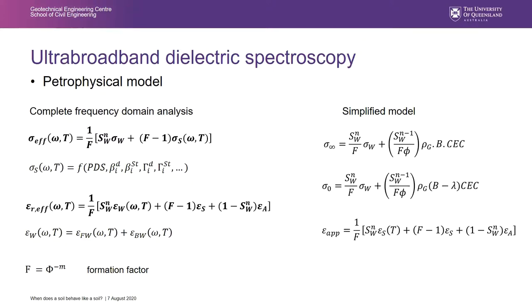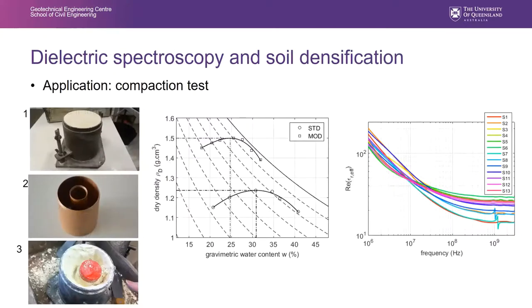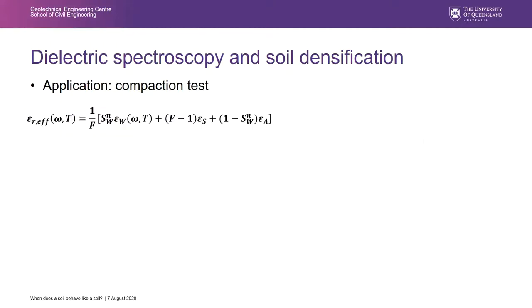So can you move to the next slide, Alex, please? We've been using this kind of method to reach density and water content, which is our fundamental aspect. Our idea is to use classical standard tests and try to compute the permittivity from the standard test. In this case, we've been measuring the compacting properties of kaolin with different water contents. You can see that for each sample, we're able to get the electromagnetic properties here.